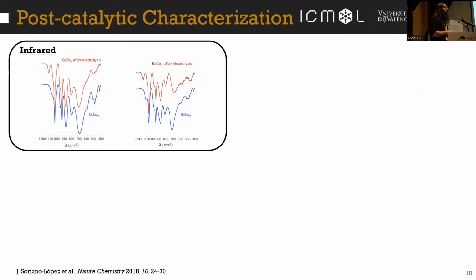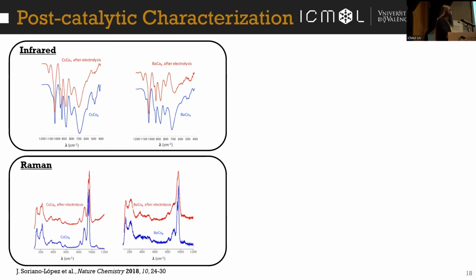Then we recovered the catalyst and characterized it. Infrared is very powerful with polyoxometalates because every polyoxometalate has a distinct fingerprint. Here we can see that before and after, the catalyst remains almost the same. Raman is also very interesting for us because with Raman we can see if we have any oxide formation. And here we can see that before and after, they are the same.